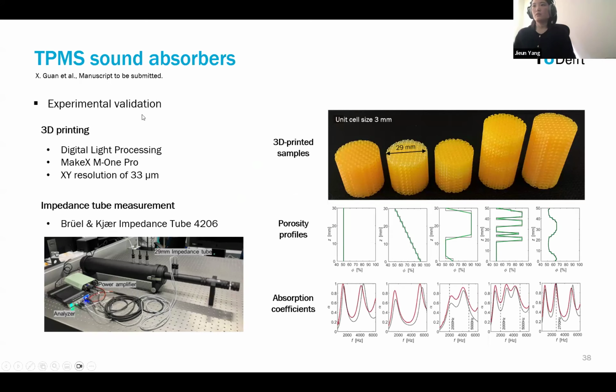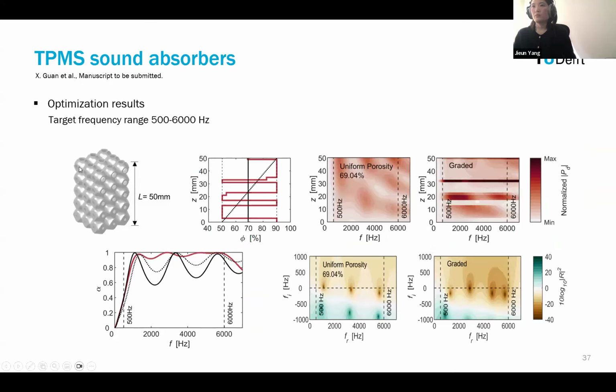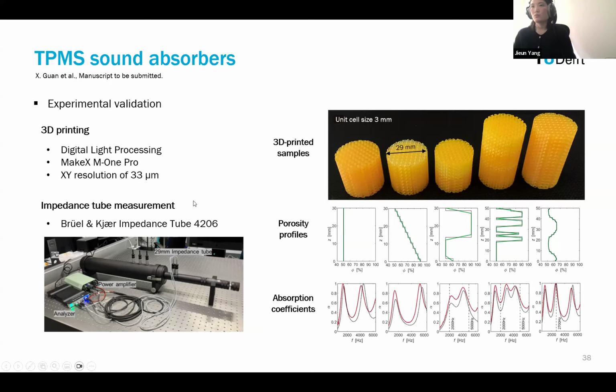And then we also did experimental validation of this work. So we 3D printed these samples using digital light processing, with this 3D printer. The resolution of the 3D printer that we used was 33 micrometers. We used a 1 millimeter unit cell for our simulation, but it wasn't really possible to print the samples with a 1 millimeter unit cell. So instead, we used a 3 millimeter unit cell. And then we conducted measurements using this impedance tube. And we did measurements for different types of porosity profile: one with just a single porosity, one linearly grading, one with a little bit of jumping type of porosity, the optimized one for this 50 millimeter layer, and also this sine wave type of porosity profile.